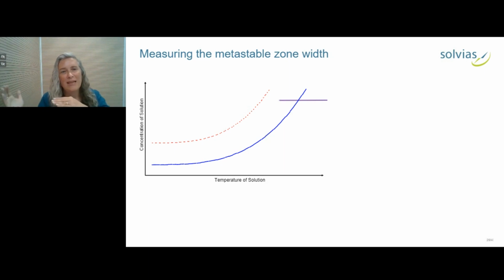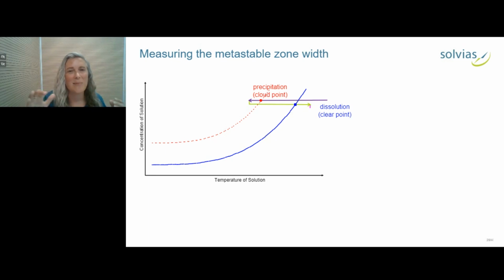You start with a high temperature, you have a solution, and you lower the temperature until you observe precipitation. The solution becomes cloudy. It's the so-called cloud point. Then you raise the temperature again. You have this cloudy solution, and you note the point when it dissolves again, the so-called clear point. And the dissolution points are on the solubility curve, and the cloud points represent the edge of the metastable zone. And then you can dilute the system and repeat the process. So lower the temperature again at this lower concentration until you see the cloud point, and then raise the temperature again until you see the new clear point and dilute again.